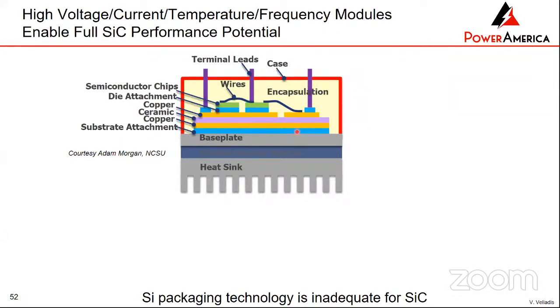You fabricate a device, and then it has to be put into a module before it goes into the system. I wanted to bring your attention to the fact that with silicon carbide, you have high voltage, high current, high temperature, and high frequency all at the same time. So if you use modules that were made for silicon, they will not work well. You will not be able to take advantage of the great performance of silicon carbide. So it's a big opportunity for module development, where you need to build modules specific for silicon carbide, meaning modules that can do high voltage, high current, high temperature, and high frequency.